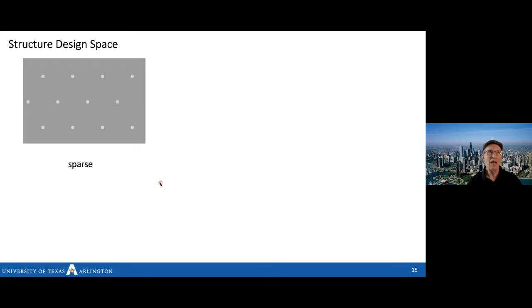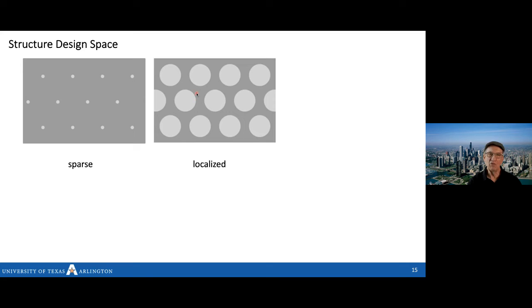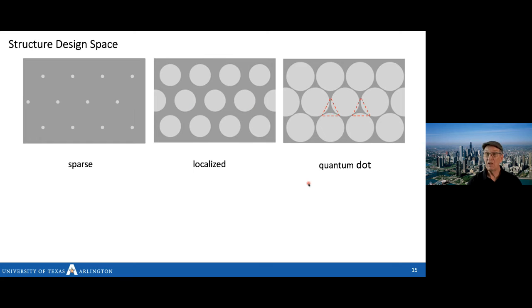So you have the ability to engineer with your pattern how you want this to look. So we can make a sparse pattern where there's little holes and widely separated. We can do localized, where we have medium-sized holes and medium-sized separation. Or we can make what looks like a quantum dot by having very large holes close together, so that basically these areas will pinch off and produce a sort of a squished triangular shape dot of material. So this allows you to shift with your pattern and change the amount of quantum-like confinement that goes on.